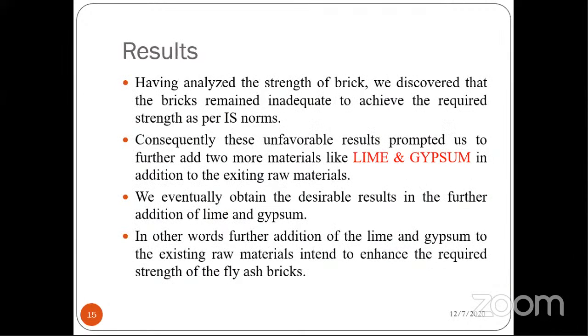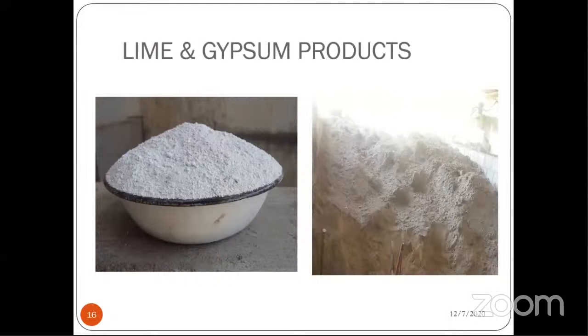And the results. Having analyzed the strength of the brick, we discovered that the brick remained inadequate to achieve the required strength as per the IS norm. So we planned to add 2 additional materials, lime and gypsum, in addition to the existing raw materials. We eventually obtained the desirable result with the further addition of lime and gypsum. In other words, further addition of lime and gypsum to the existing raw material is intended to enhance the required strength of the fly ash bricks. And these are the images.